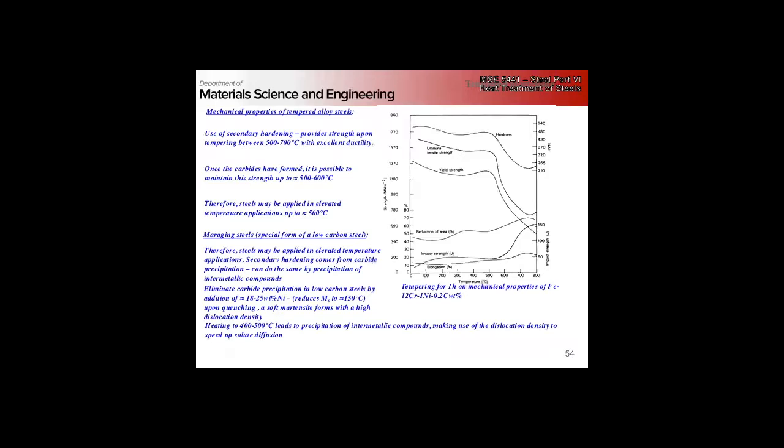And this is just the kinetics here, right? So we make good use of secondary hardening, right? Once the carbide forms, you can temper up to, say, a range of 500 to 600, and still keep your high strength values. Once you get above that, we either dissolve or grow our carbides to the point where they're not effective, right?